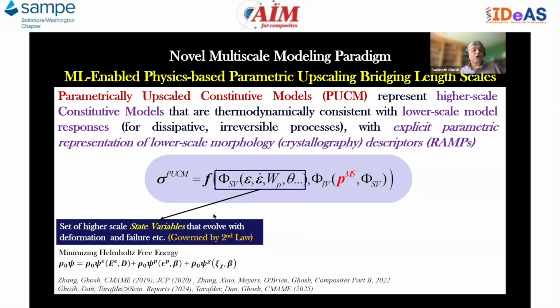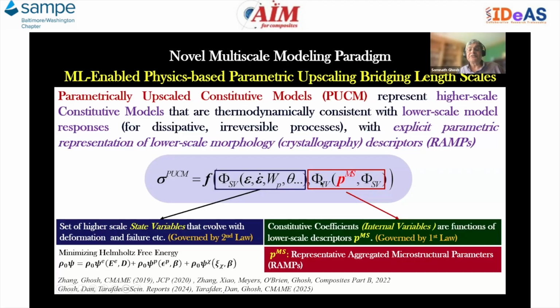Now, the overall form, including the set of higher scale state variables, for example strain rates, the work, the damage work, temperature dependence, that evolve with deformation and failure, are governed by the second law. For example, one can use the Helmholtz free energy and minimize it to obtain this form. But this is more important here: the constitutive coefficients are coefficients of internal variables. These are internal variables that are functions of lower scale descriptors. When I say lower scale descriptors, I'm going to be addressing them as representative aggregated microstructural parameters. We will call them ramps. The ramps represent lower scale descriptors, and I'm going to give an example of this. And this part is governed by the first law.